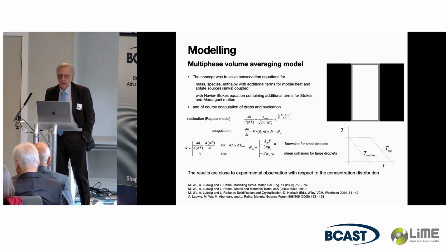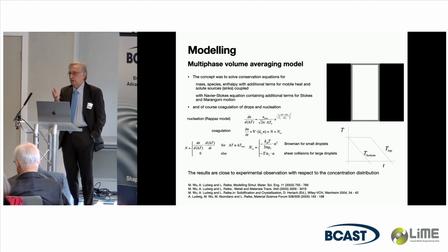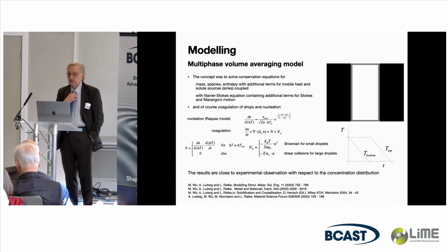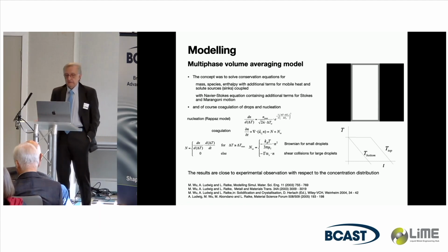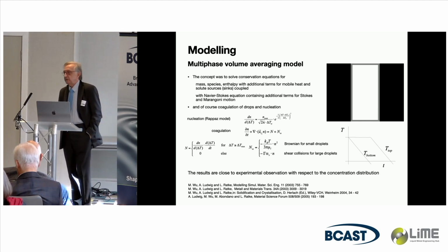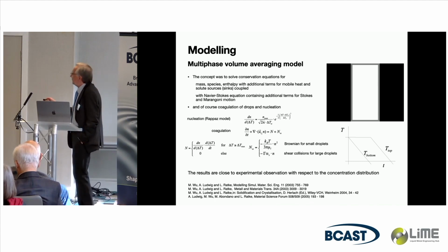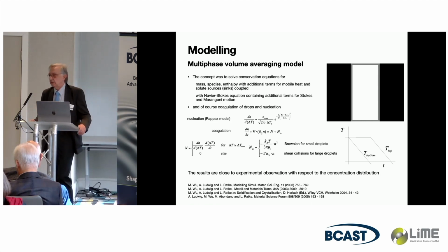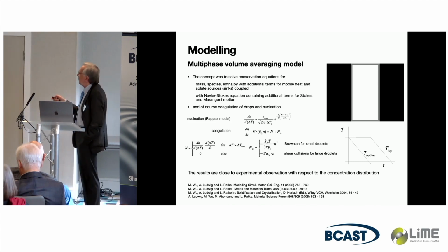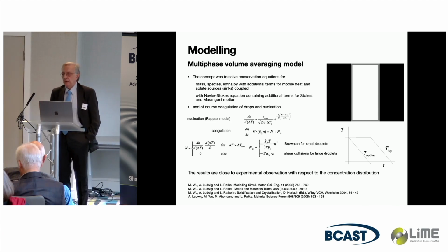Because we then thought, when we had this project where Lars Arnberg and Reinhard Mattison were also involved, we had a nice joint project because, with two companies together, we would like to develop aluminum lead or aluminum bismuth better bearings. And Meng Huai Wu and Andreas Ludwig said, well, we can model that. And what they did is, of course, they used the multi-phase volume averaging model, which in principle goes back to Viskanta and Christoph Beckermann in the 90s. They extended this with mobile heat and solute sources or sinks, additional terms for Stokes and Marangoni motion, and of course described coagulation of drops by either Brownian motion or by shear collisions. And of course you put in a nucleation model going back to Rappaz, as I mentioned.